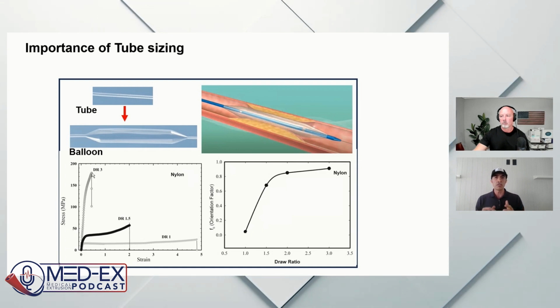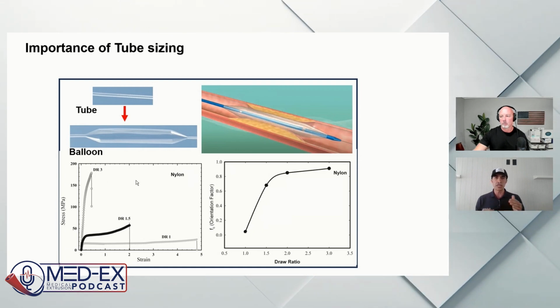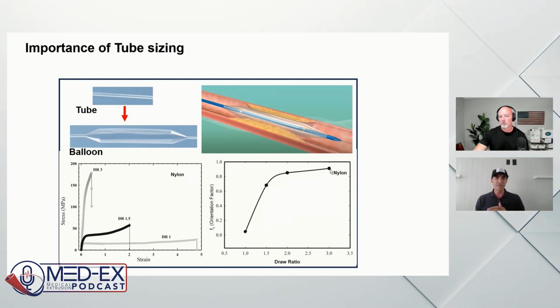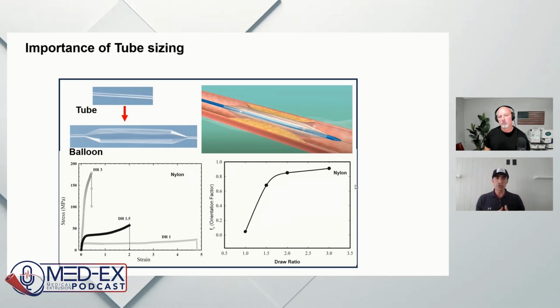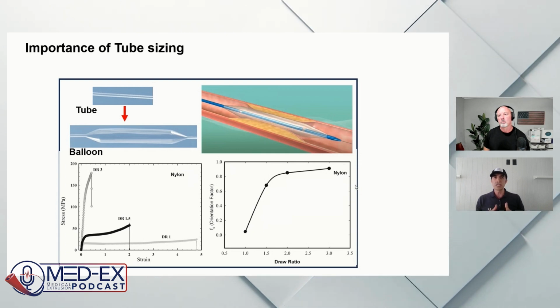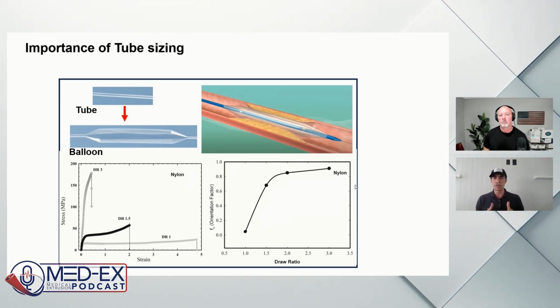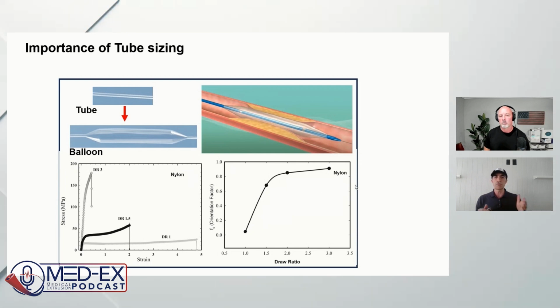Mm-hmm. The graph on the bottom right shows that the orientation function after an expansion ratio, or drawdown ratio, of 3 basically reaches a plateau. So any further stretching would just decrease the thickness of the balloon. The mechanical properties and orientation function after that basically reach a plateau.